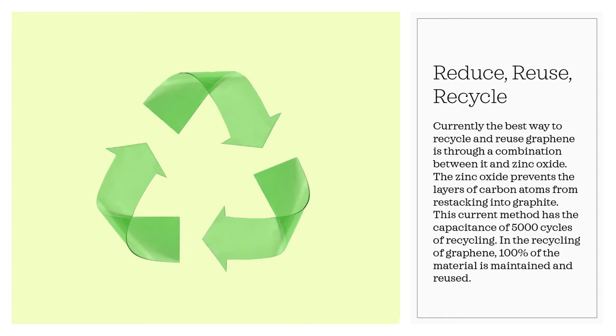Recycling. So in order to recycle graphene, it is combined with zinc oxide, and the zinc oxide keeps the graphene layers from separating and from joining together and becoming graphite. It keeps it separated. So this can be done for about 5,000 cycles. And during those 5,000 cycles, 100% of the graphene can be maintained and reused.